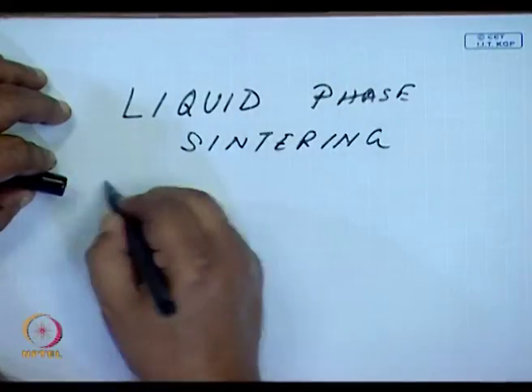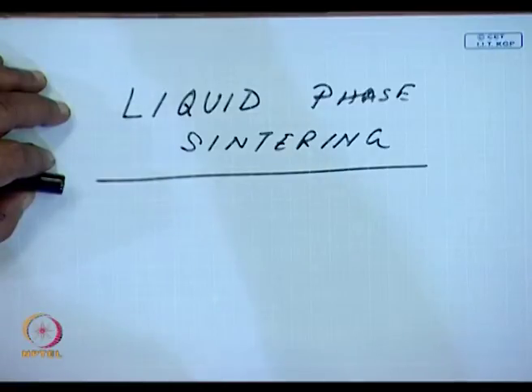While I did say that liquid phase sintering has got its own drawback, that is, it gives us a glassy phase at the grain boundary, which will lead to mechanical failure or low temperature stability, that is, may soften at lower temperature, yet liquid phase sintering at times is our mainstay of sintering. There are systems which cannot be sintered other than in the liquid phase, other than without generating a liquid phase.